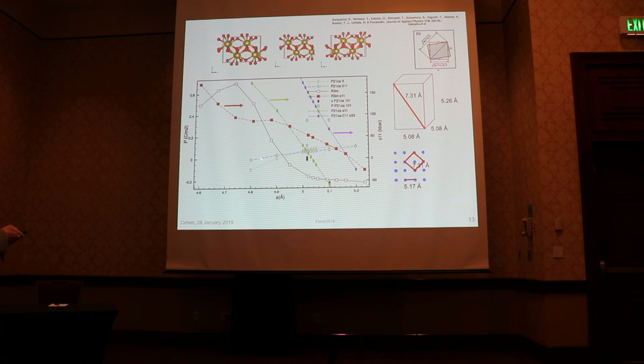Here, the green and blue are different versions, one with the polarization out of plane and one with polarization in plane, and this is again with epitaxial strain. And then this is the rhombohedral phase that Noheda's group talked about. You can see it has a much higher polarization, but only at very high compressive strain. So whether you could